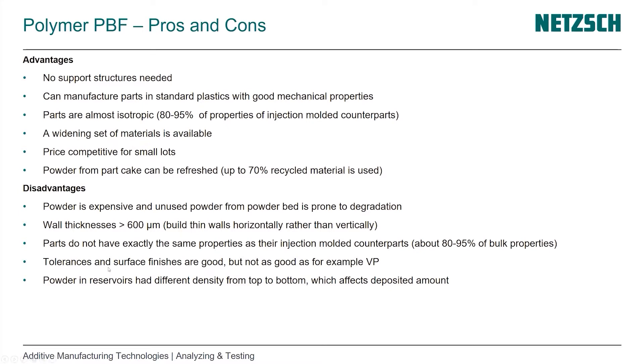Structural parts are also possible because of its isotropic behavior. We don't see a huge difference in the strengths and modulus in different directions of the part. In fact, depending on the process parameters, you reach 80 to 95 percent of the properties of a homogeneous injection molded part.